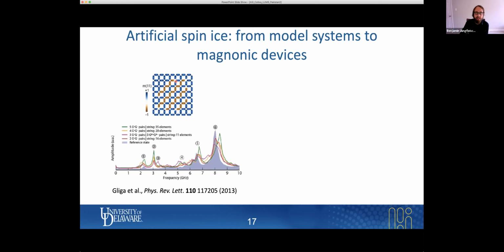For example, here it's a type 3 state. And these monopole anti-monopole pairs are connected via a string. And these strings are shown here in this brownish color. That's essentially a chain of flipped spins. And what they found in their simulations is that dependent on the number of strings and the number of monopole anti-monopole pairs in the lattice, certain modes appear in the resonance spectra.